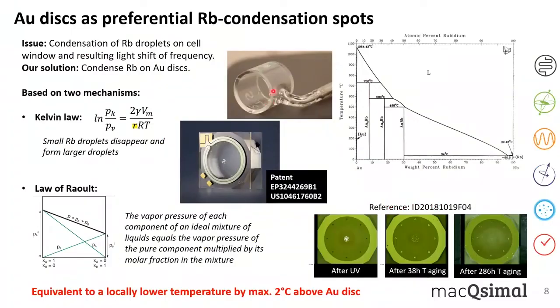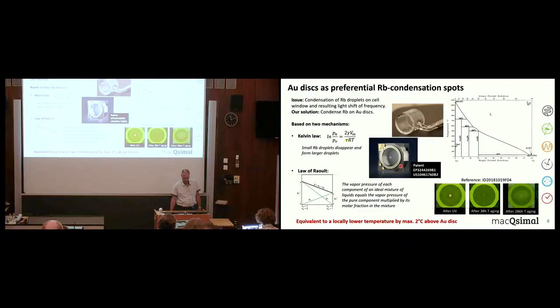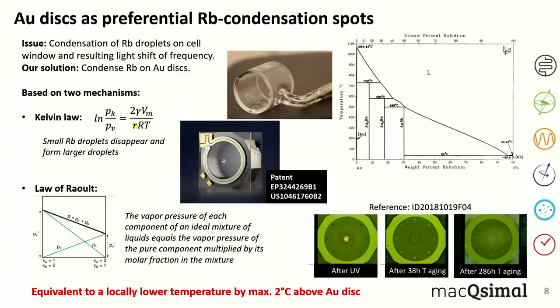You can heat them maybe locally here, and in this example here, they have the stem where they put the rubidium in, and they just leave the stem, and this is then some kind of cold spot where all the rubidium will condense. So it will condense here and not on the cell window. This technique is much more difficult for a MEMS vapor cell because the dimensions are smaller. This cell here has dimensions of 4 by 4 millimeter and a thickness of 1.9 millimeter. So obviously here it is very difficult to introduce a temperature gradient.